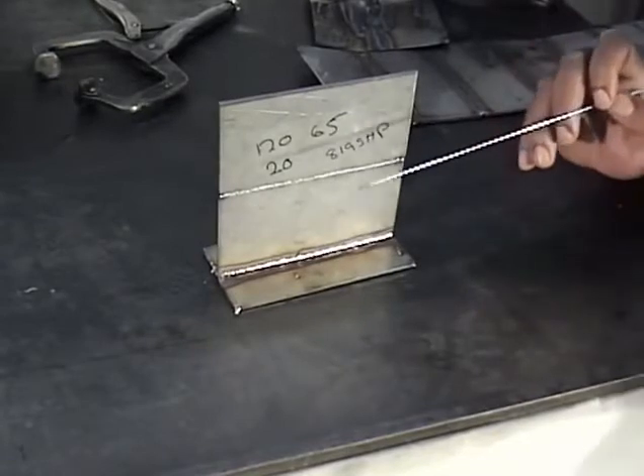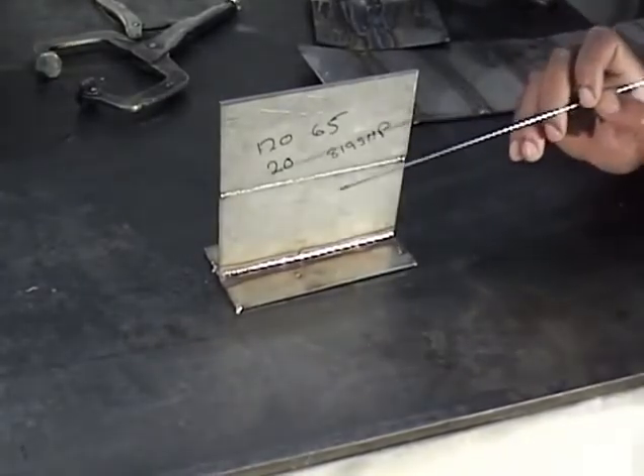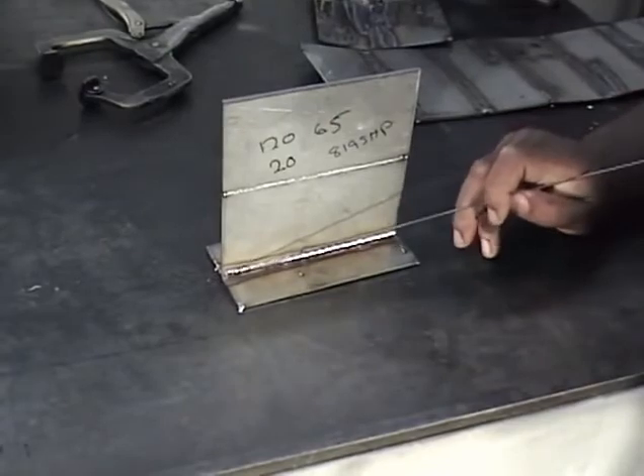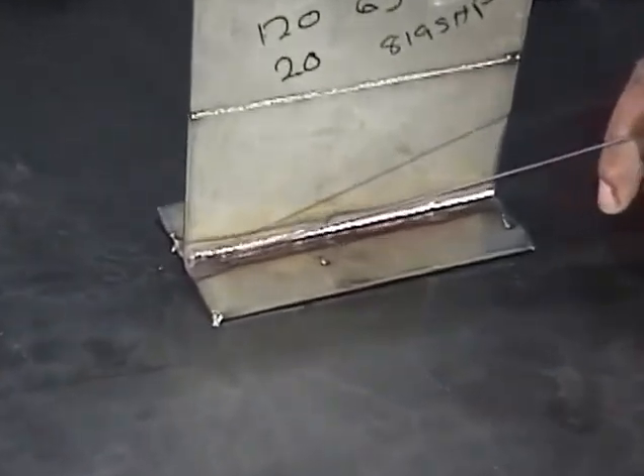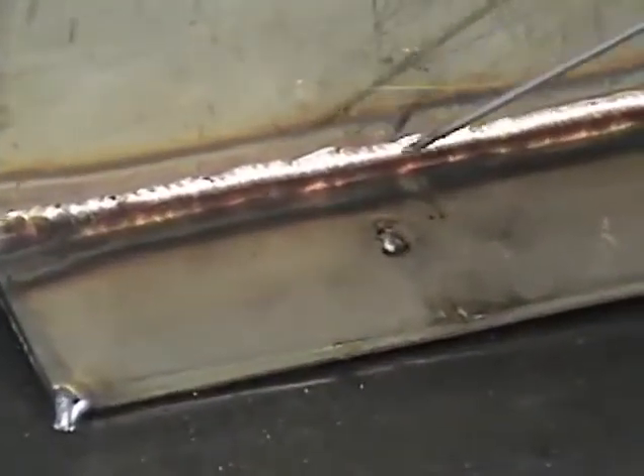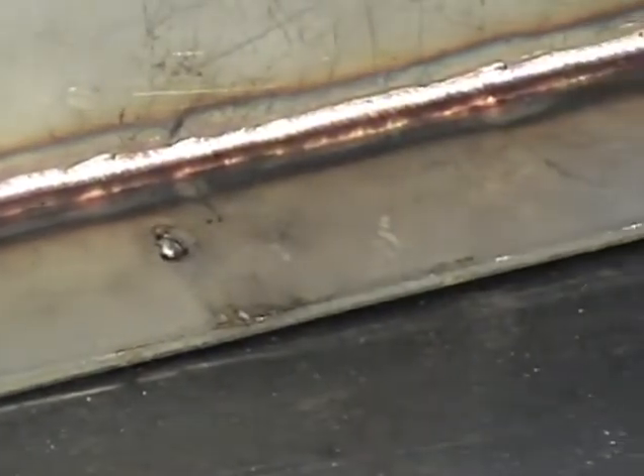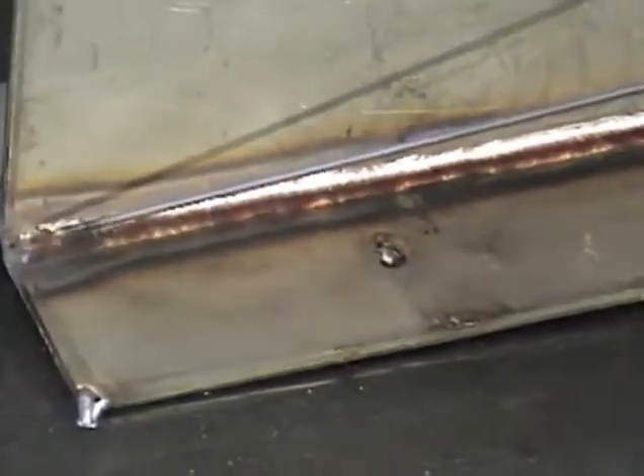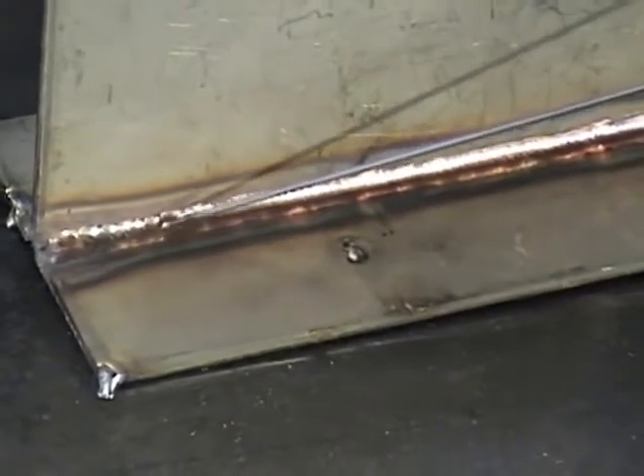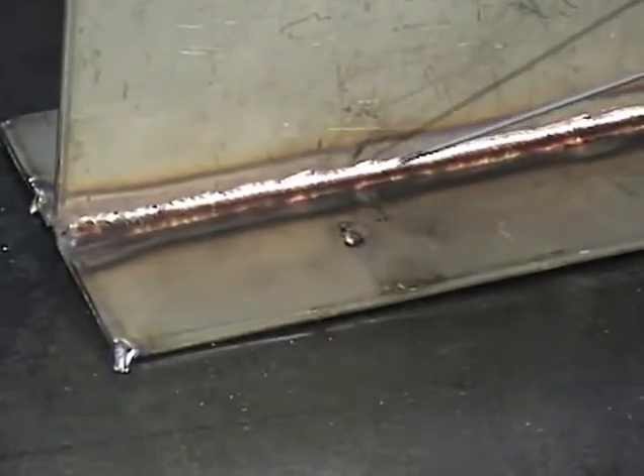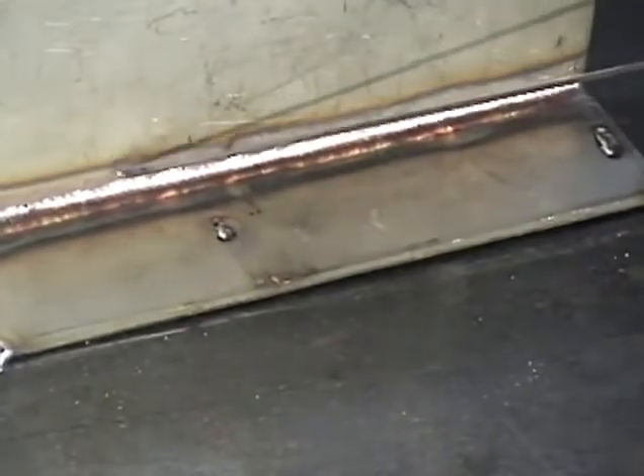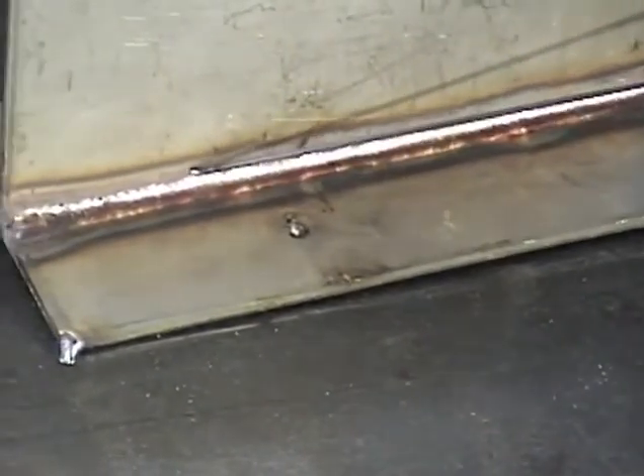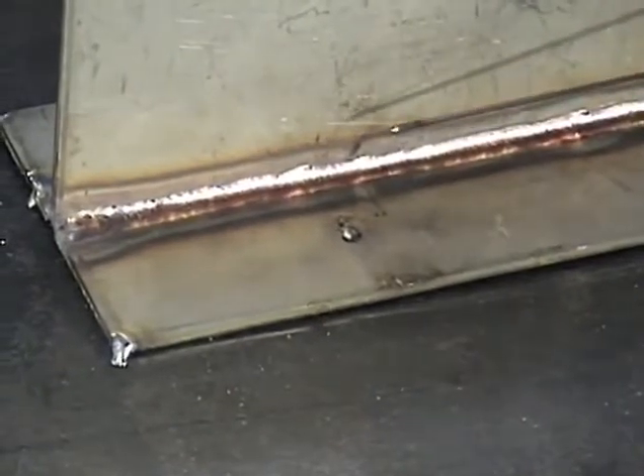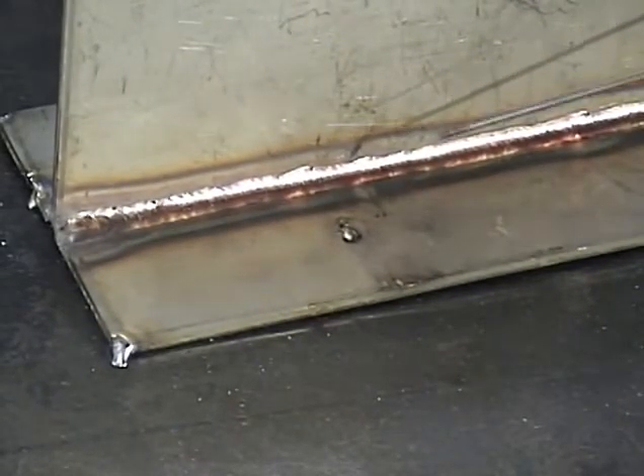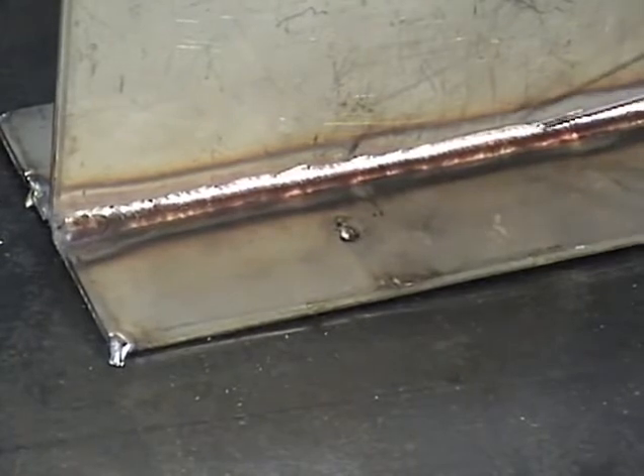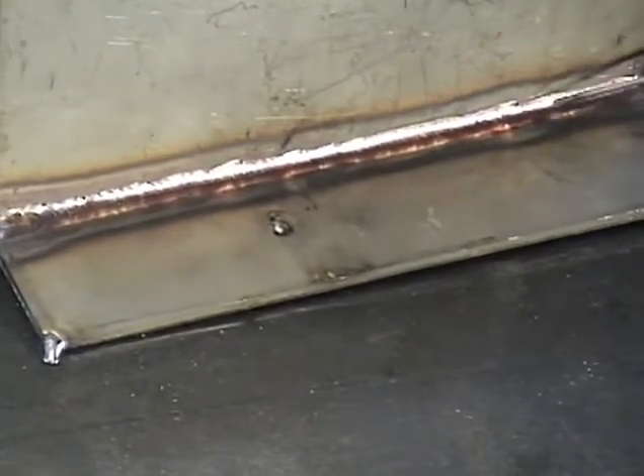Okay, we just finished our T-joint in 316 stainless steel. And this is what you should look for. This is what a finished weld looks like. It has pretty colors, the reds and the blues and straws. You don't want any black. You're looking for each bead to be locked in behind the other one. You want everything to be clean. You want the toe of the weld, the edges of the welds, no undercut, and the appearance is nice. The appearance is a pretty weld. That's what you're looking for.